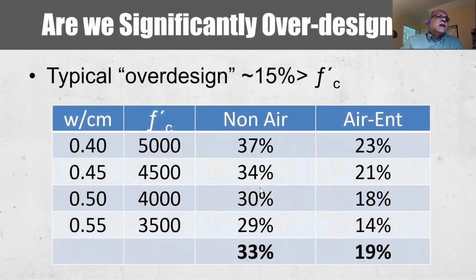And what we see in a general survey of the ready-mix industry is that while you have design strengths, the associated water cement ratios are more in line with air entrained concrete. While the typical over-design is about 15% greater than the design strength or specified strength, you'll see that in many cases you are significantly over-designing based on just the water cement ratio type of limit, to produce an average strength much higher than required.